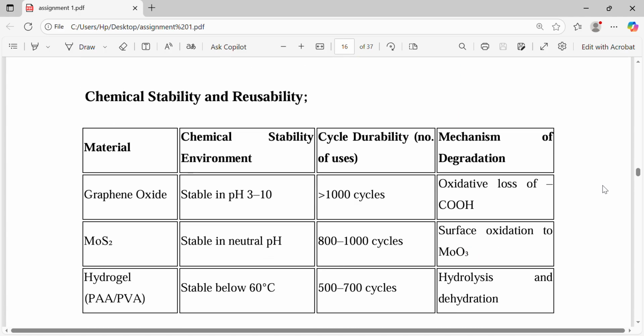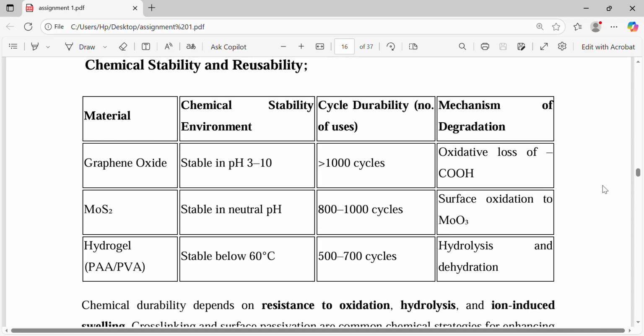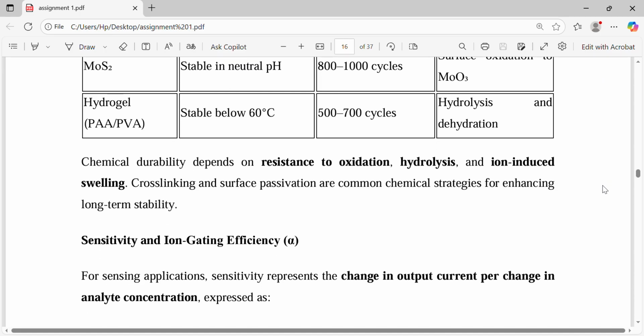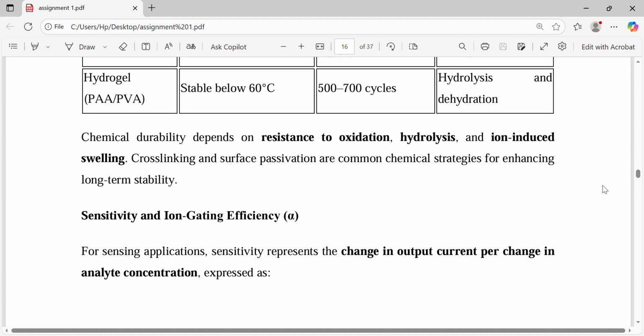Chemical stability and reusability. Graphene oxide is stable in pH 3 to 10; MoS2 is stable in neutral pH. Hydrogels stay stable below 60 degrees Celsius. Cycling: 1000 cycles, 800 to 1000 cycles, 500 to 700 cycles. Degradation: oxidative loss of COOH, surface oxidation to MoO3, hydrolysis and dehydration. Chemical durability depends on resistance to oxidation, hydrolysis, and ion-induced swelling. Cross-linking and surface passivation are common chemical strategies for enhancing long-term stability.